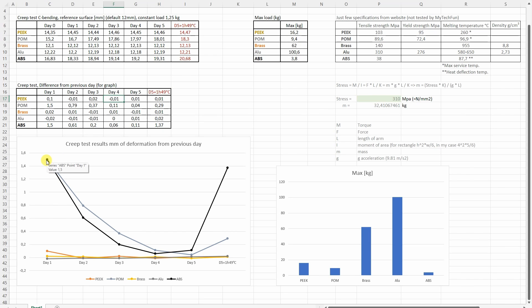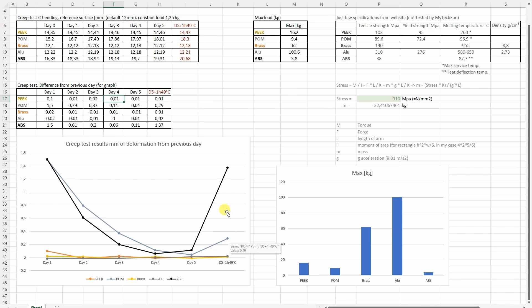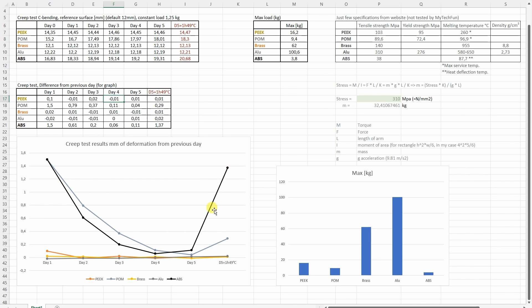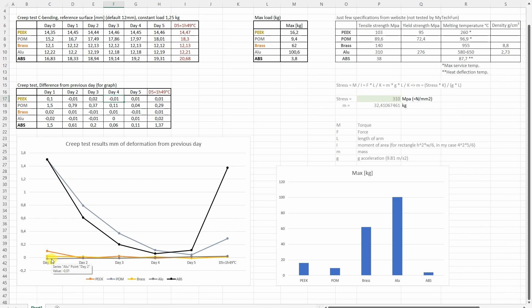Okay, so what can we see in this graph? The POM and ABS start with quite a lot of creeping and only after fourth or fifth day it's stabilized. But after one hour in a heated oven we can see some deformations on the POM and quite a lot of creeping on ABS. This is one of the cheapest ABS. I think it's Geetech Builder or something like that. But very pleasant surprise was the PEEK. Very minimal deformations after one day. But after this almost no deformations at all. And of course with the brass and aluminum, it was no surprises that there was no deformations at all, almost.